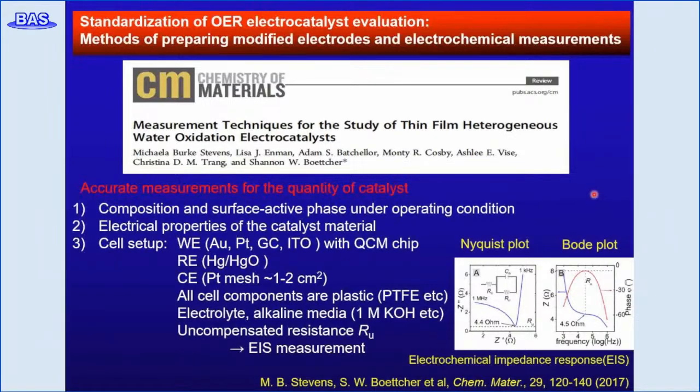It is also important to investigate the conductivity of the catalyst when it is fixed on the electrode surface. For the electric cell, the working electrode should be gold, platinum, or glassy carbon.